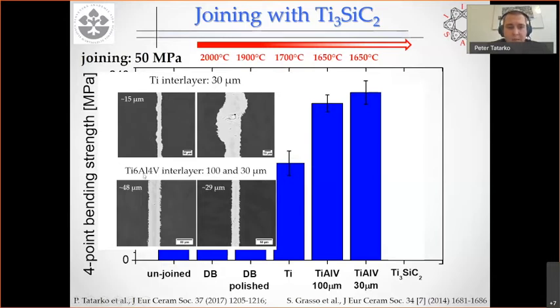In this case, aluminum vanadium, we also used 100 micrometers, and especially for the first case, you see again almost 50% shrinkage. So it was very, very dangerous because it can produce high residual stresses in your material, and that's why it explains a lower strength than in the case of the 30 micrometer foil.